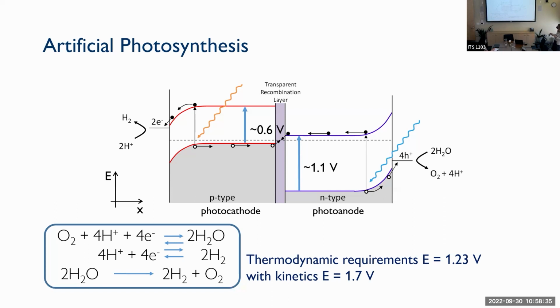So when you have an N-type material and you put it in an electrode and you shine light, you will have bending at the interface. And this bending allows holes, specifically for an N-type material, to go to the surface, and the holes are utilized to oxidize water. Similarly, at a photocathode material, you have downward bending, and you have electrons that are going to the surface. Now you can utilize those electrons to reduce a chemical. And so now you reduce water to hydrogen, or you reduce carbon dioxide to other chemicals.